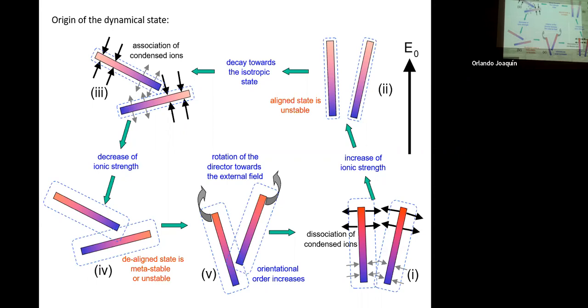And it will decrease to an extent that the effective concentration is not high enough to stabilize the nematic state. So the nematic state becomes unstable and the domain will melt, becoming isotropic again.